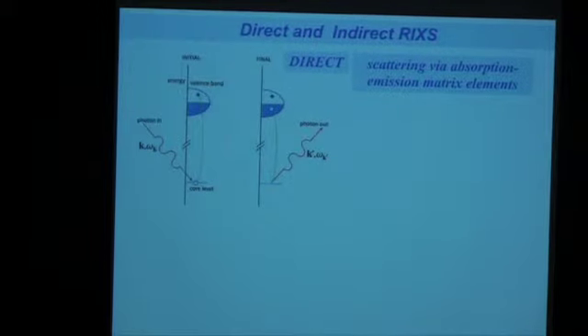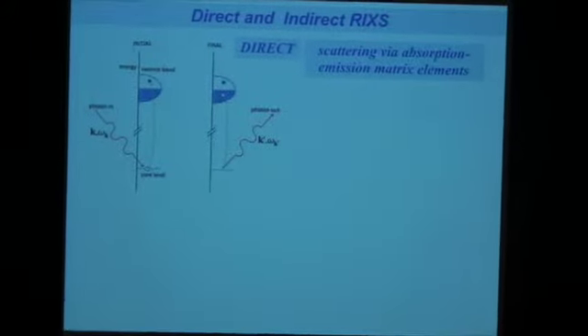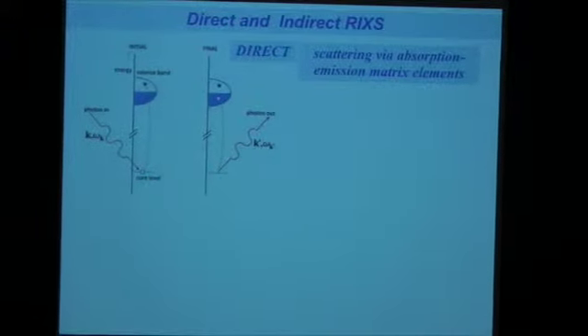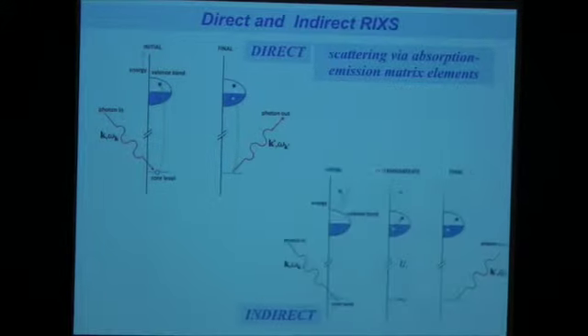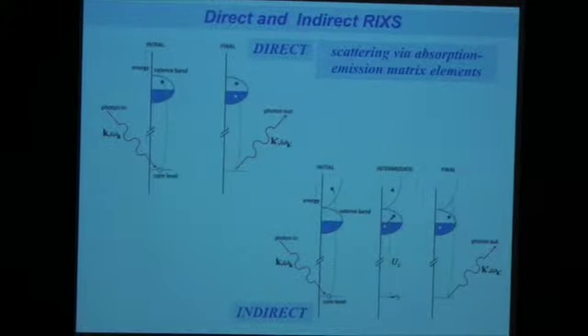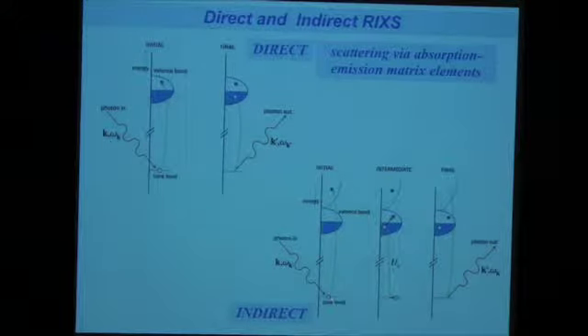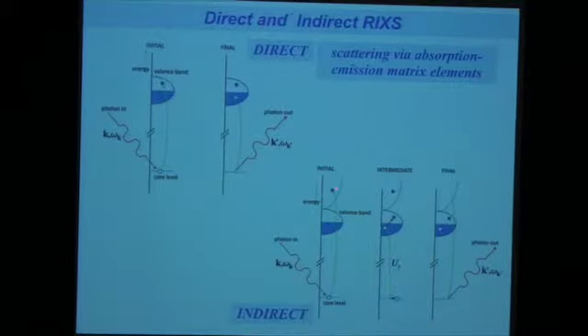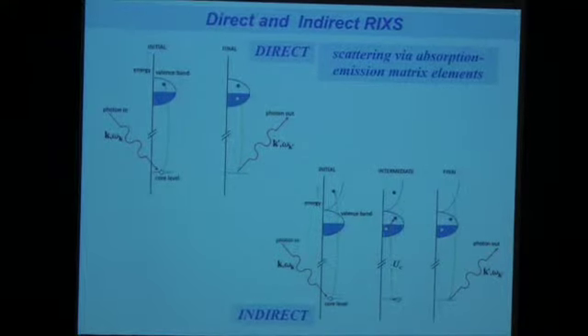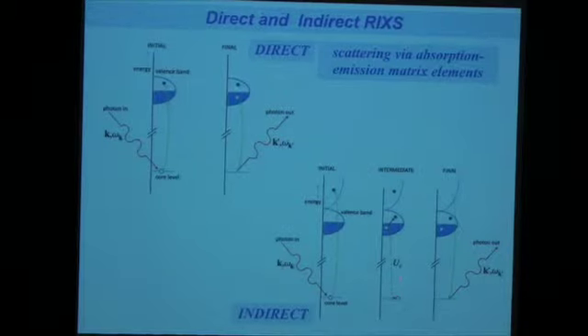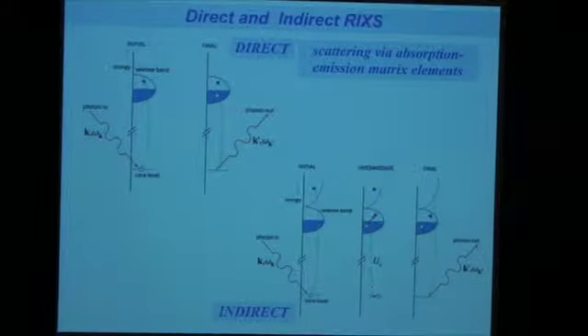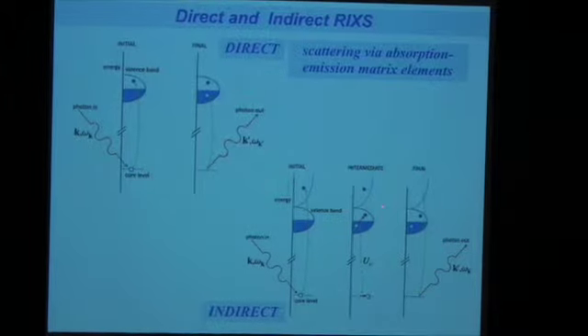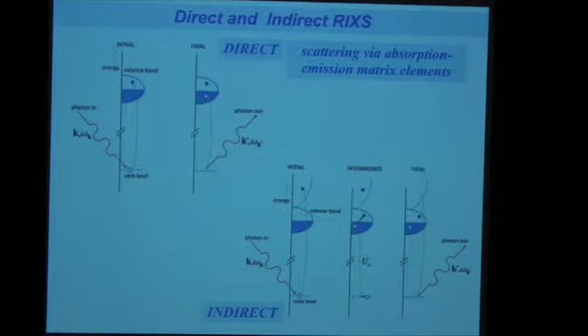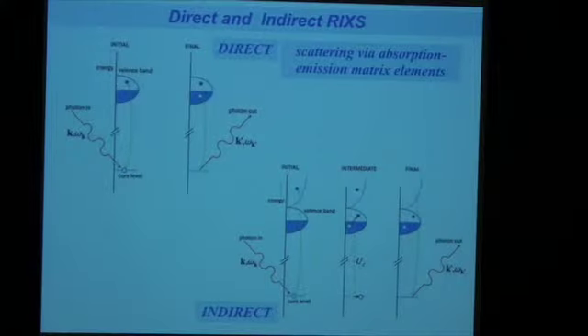The scattering, in this case, I would say, occurs via absorption and emission matrix elements, basically. At least in leading order, that's what happens. If I have indirect RIXS, it's a bit different because now the photon comes in, excites the 1s electron into the 4p state high above the Fermi level. And while this core hole is present, the core hole scatters electrons at the Fermi level, makes electron-hole excitations there. So it's the potential of the core hole that gives rise to low energy excitations.